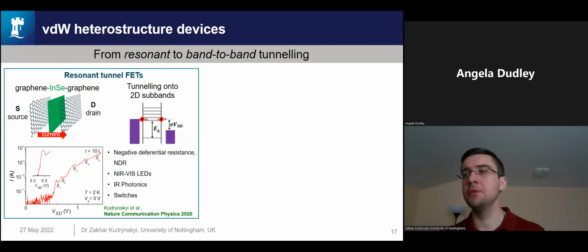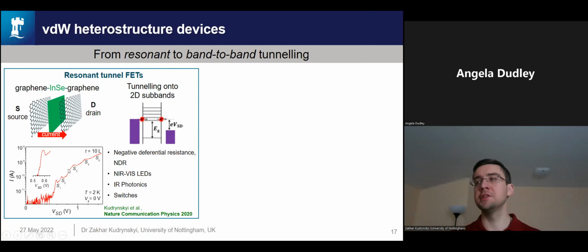I also want to give you an overview of other heterostructures that we have been looking at recently, starting with a resonant tunneling field effect transistor, where you can see an indium selenide layer is embedded between two graphene electrodes, the source and the drain. Here we have studied the resonant transmission of an electron through a 2D subband in indium selenide, and observed these regions of negative differential resistance in the current voltage characteristics that can be tuned by the Fermi level in the graphene source.